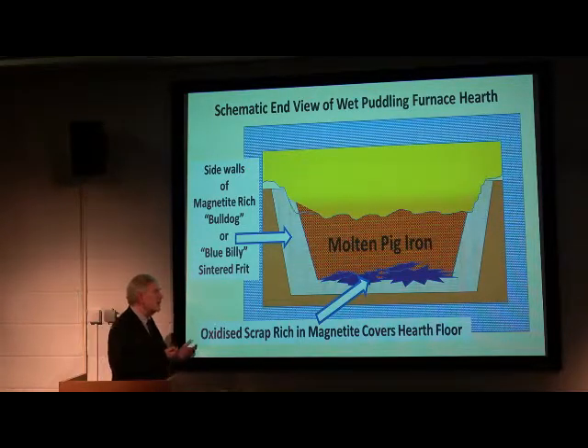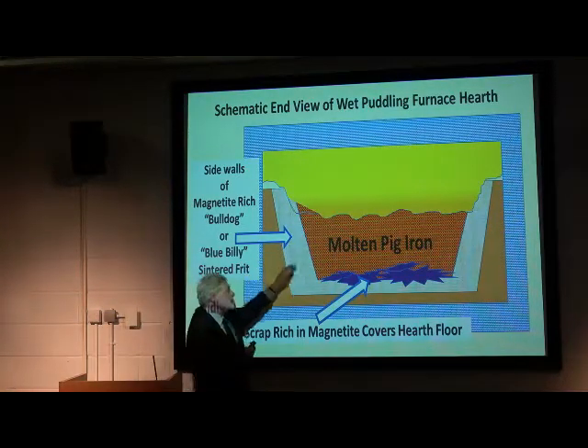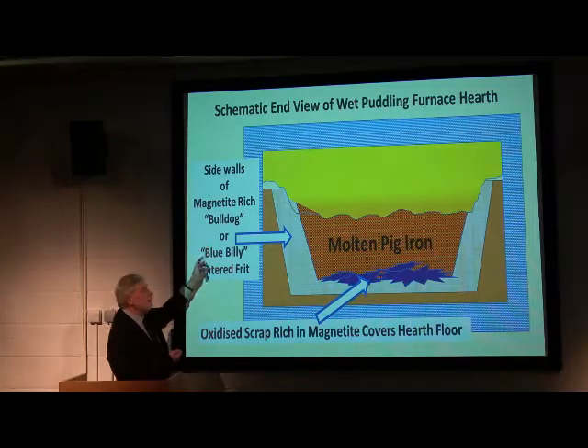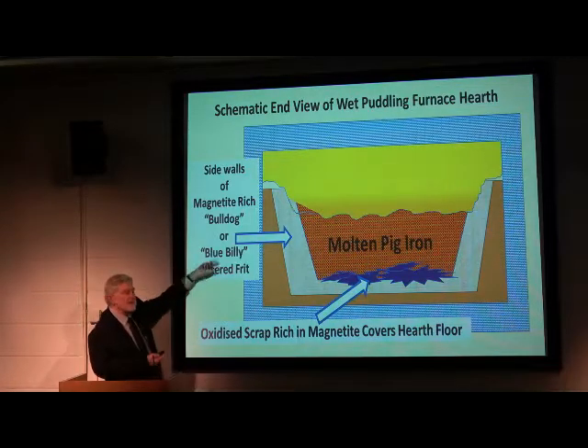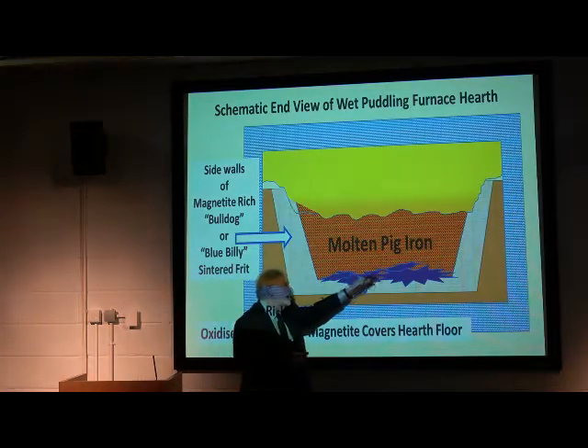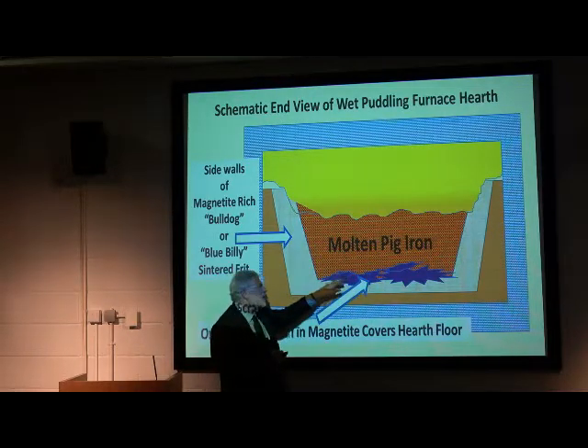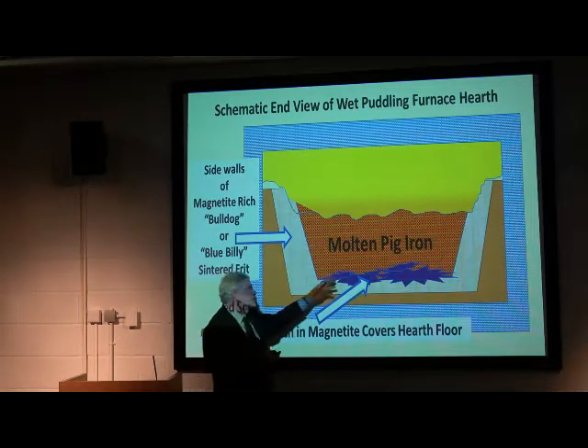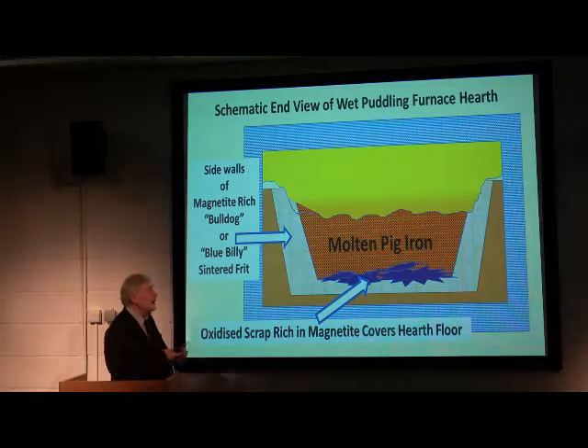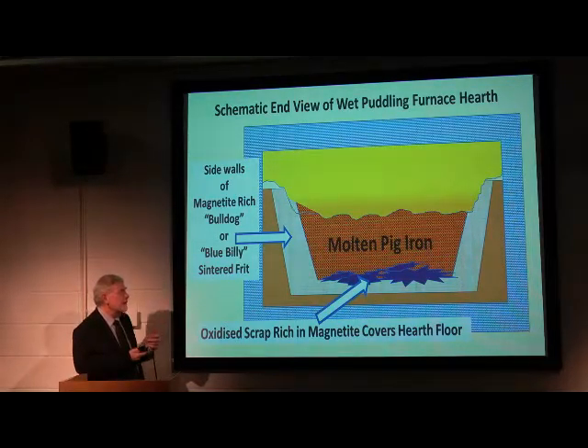What they did with wet puddling is that they made the sides of the enclosure out of material called bulldog or blue billy. These are effectively refractory materials containing a lot of magnetite. We start off the process by filling the bottom of the system with scrap iron. You heat it up, that turns into magnetite, and then during the process the magnetite reacts with the carbon, silicon and phosphorus in the iron.